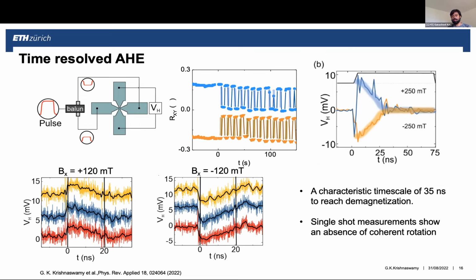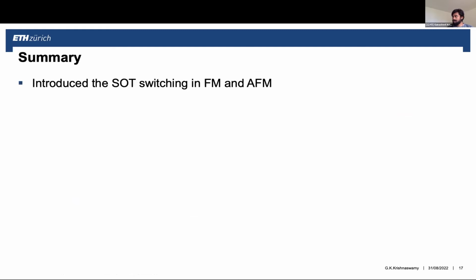And then during the cool down, as soon as the antiferromagnet goes below the Néel temperature, the spin-orbit torque acts very efficiently to switch it from whatever state it is in to a deterministic up or down or intermediate state during the switching.